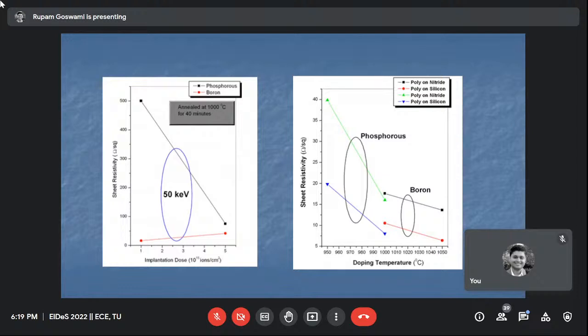Here, in the first slide, you can see how the sheet resistivity of the film is controlled. This is boron implantation, and this is phosphorus implantation. At 50 keV, the phosphorus was implanted in the 0.5 micron LPCVD film, and it was annealed at 1000 degrees for 40 minutes. This is very amazing data.